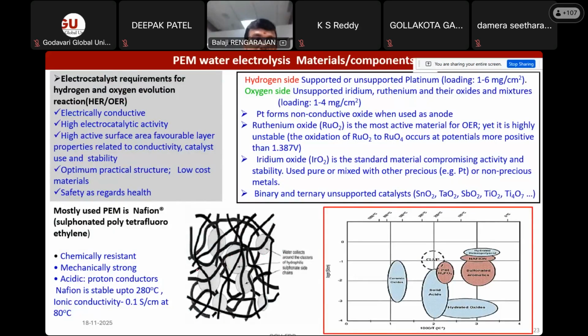The beauty is that it will conduct protons in the presence of pure water, it reduces the inter-electrode distance, and it will also separate the gas molecules. So the property of it should be that it is electrically non-conductive but highly ionic conductive. It should have zero electronic conductivity and high ionic conductivity. That is one of the main properties of this membrane, and it should have high mechanical strength and thermal stability. In terms of temperature, when you circulate the water, you cannot operate the cell beyond 100 degrees Celsius, because beyond 100 degrees water will evaporate. So it should be operated below 100 degrees Celsius, and at that operating temperature the membrane should be stable. So this is one of the main components of a PEM based electrolysis cell.